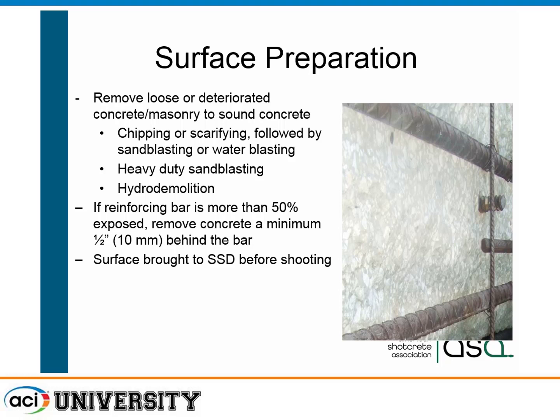If less than 50% of the bar is exposed, if you have just half the bar showing, it's okay to go ahead and encase that with shotcrete. If there's more than 50%, we like you to excavate back behind the bar so that we can get shotcrete back and actually tie that in. We also want to bring the surface to saturated surface dry. That means that it's wetted. We fill the pores of the concrete surface with water, and when we shoot against it, we drive that paste into the surface. It's not really diluted. It allows more of the hydration right at the surface. If we have running water, it's going to be too diluted. We're going to lose some of the bond. If you shoot against bone dry concrete, what's it going to do? It's going to suck the water right out of the paste, right at that interface, and that also can reduce bond.